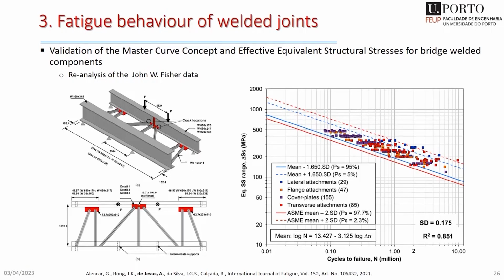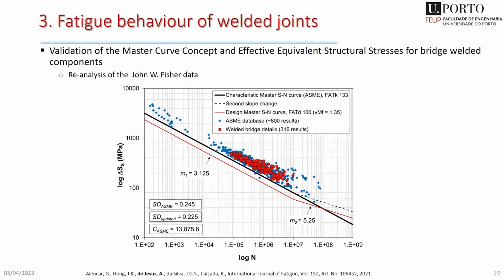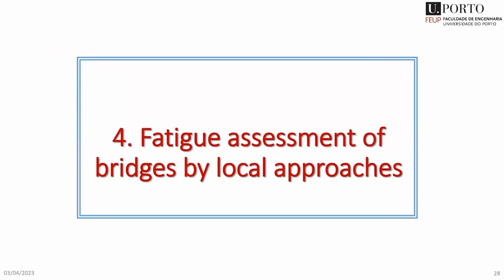So we were able to match all the data together. That's the most important message. And again, we superimpose these on the pressure vessels, and we found a very good correlation with the previous database. So we are adding more or less 300 points to the existing database. So for the moment, we can say this is robust for pressure vessels and welded bridges, where we have special multi-axial loading cases.